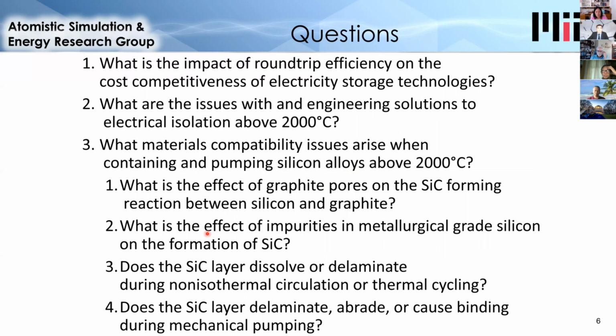The second question was whether there's an affordable grade of silicon that can be contained. And so the more impurities that are allowed in the silicon, the cheaper it is. So we investigated several grades of silicon. The third question involves whether the silicon carbide layer that forms when silicon and graphite react remains protective. So this layer can form a barrier preventing further reaction under certain conditions. And we wanted to know, does it remain protective under non-isothermal circulation?